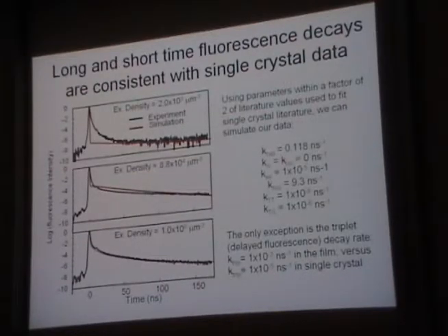So we stay with the fluorescence and we say, well, in the old days, everybody measured fluorescence of tetracene crystals. Do our results on polycrystalline film agree with all those old single crystal measurements? We'd like to check that. And the answer is yes. We can do a pretty good semi-quantitative, again, this is a log plot, right?